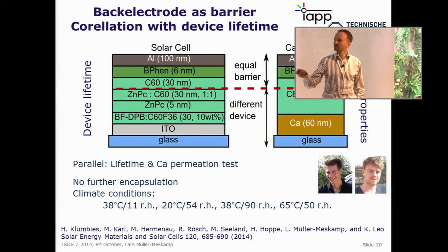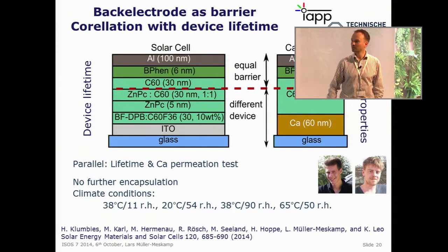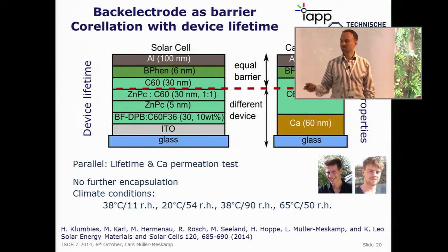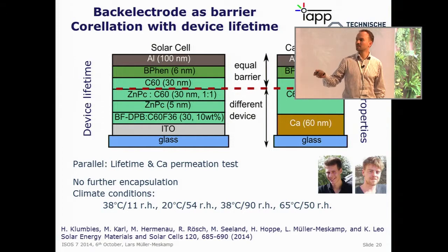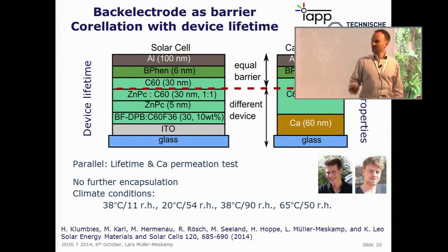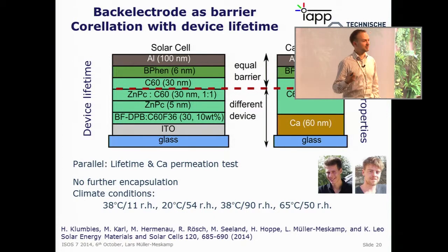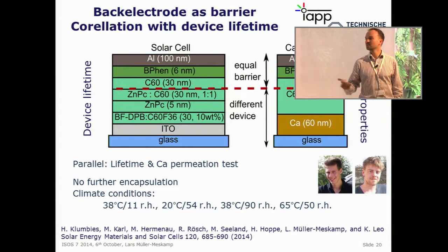So this is a nice study of Hannes, and here we have a standard solar cell. This solar cell is very stable. Intrinsically, it's good for several thousands of hours, up to 10,000 I think we have measured, and it's still okay. And we took the top layers with the aluminum electrode and the BPhen below and a bit of C60 and put them on top of our calcium test. And this aluminum electrode is a barrier. It's a quite good barrier, actually. It's around 10 to the minus 3, sometimes even 10 to the minus 4. It depends on your deposition conditions. So now we have this intrinsic barrier on top of both devices, and below we have the calcium test or we have the dying device. So we can correlate our calcium test to the solar cell.